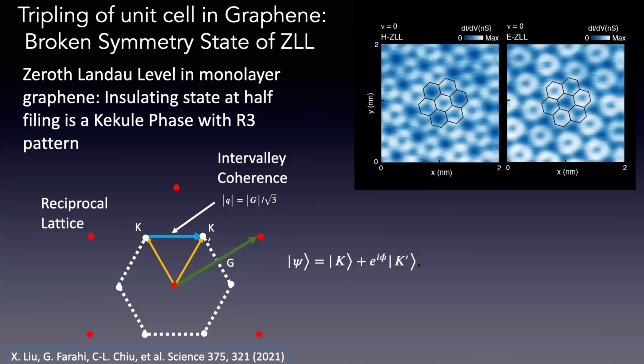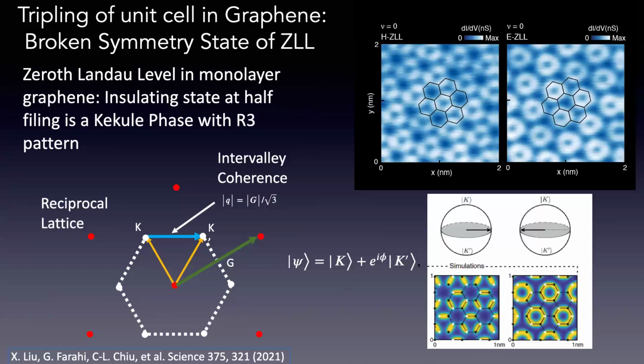This was discovered in 2010, and it was a puzzle as to what is the nature of this insulator, and we argued for a long time. And we came in kind of late to the game, but we basically imaged the states of this half-filled Landau level, and we found that it makes this tripling of unit cells, a Kekulé state. That's what it's called because this is the occupied state, this is the unoccupied state, they're sort of complement of one another. And what you see is they're lining up the electrons along the bonds between the carbon atoms rather than on the atoms. And this comes about because in graphene, you have 2 valleys, and when you make a quantum superposition of these 2 valleys, you line up the electrons on the bond.